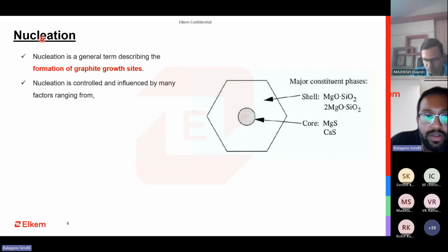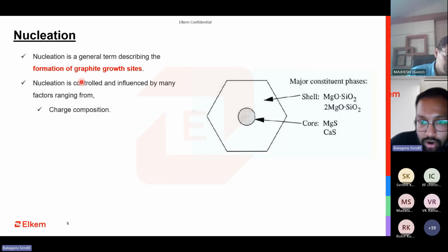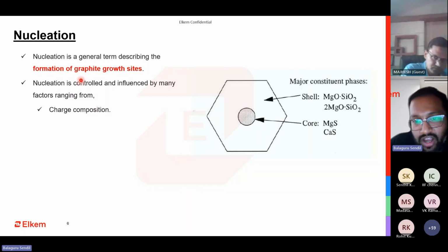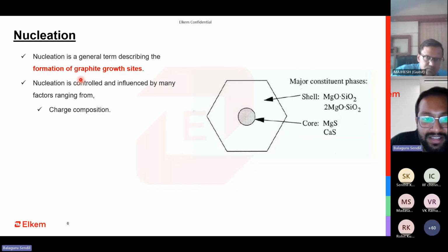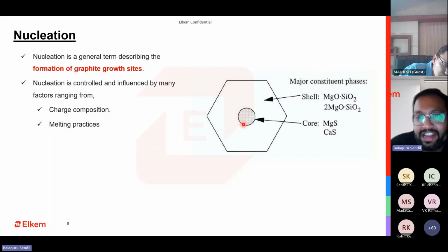So how do you influence the amount of nucleation? There are many factors which influence it. The most common is the charge composition that we are following, your carbon equivalent. How much is your carbon and silicon? This is the most basic thing that can influence it. The second one is your melting practices, the furnace that you use, the charge mix that you follow, the sequence that you use, the amount of holding that you have. All this will impact nucleation. If you are holding it for longer, then the nucleating sites that the base metal inherently has will get depleted over a period of time.